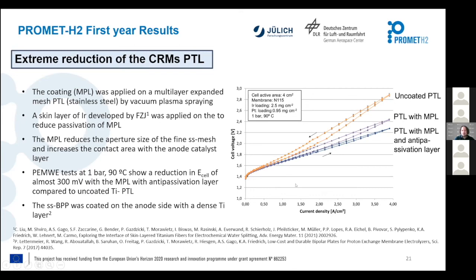As you see from the graph, we have almost a 300 millivolt difference in the potential drop of the polarization curve, which I think is quite high, more so because these materials are based on stainless steel and are much cheaper than the ones based on titanium.